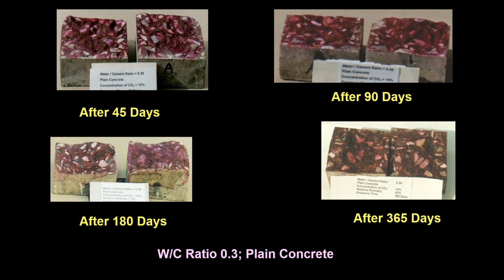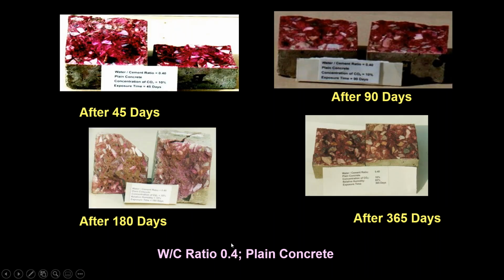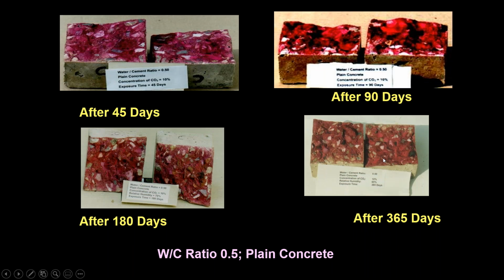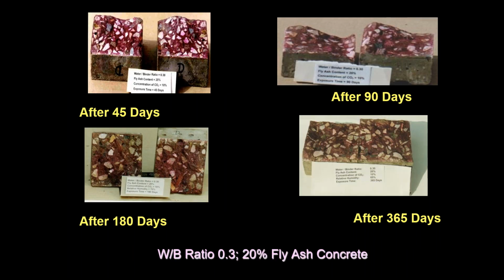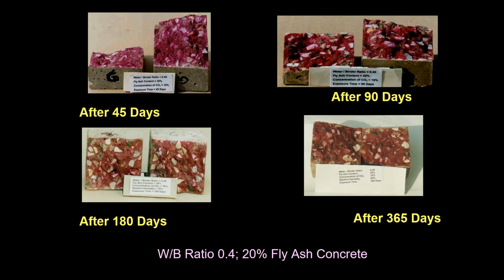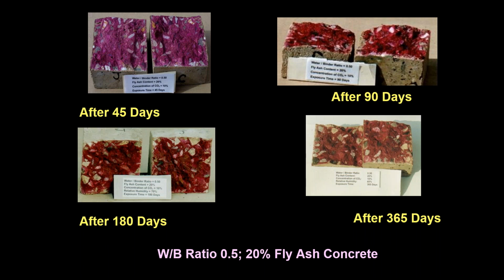Now you can see the water binder ratio 0.3 plain concrete. Even at 1 year, 365 days, no carbonation took place. And for water binder ratio 0.5 plain concrete, even after 1 year in the accelerated condition, no carbonation took place. Now you can see the 20% fly ash. Even after 1 year exposure, no carbonation took place with the 20% fly ash. And with 0.4, 20% fly ash, here also carbonation did not take place. And 0.5, 20%, here also carbonation did not take place.